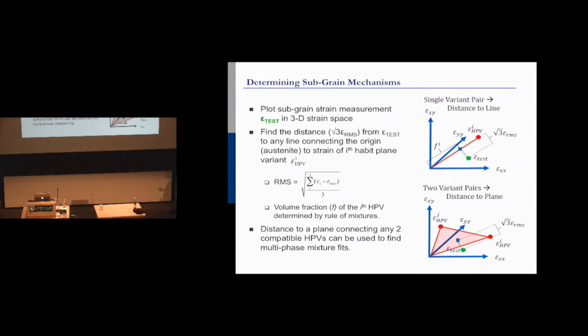You have 12 of these possibilities. You have 12 possible correspondent variants, and you have any possible mixture of them in layer cake form with the austenite. But you can plot all of that. You can imagine in strain space these interlocking tetrahedra. And it ends up being just a bunch of tetrahedra. When you plot all the strain points in a grain, they all cluster around a certain tetrahedra, and that tells you what correspondent variant is active. So you can actually say exactly this correspondent variant is active with a pretty high degree of certainty.